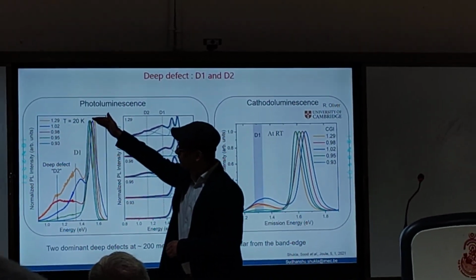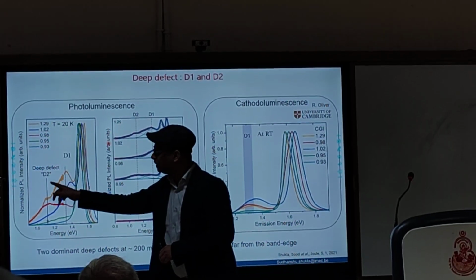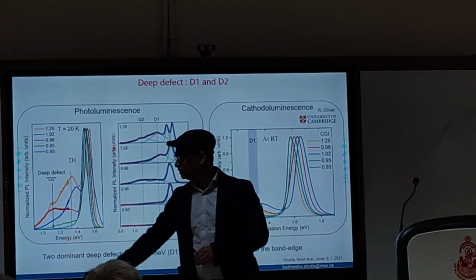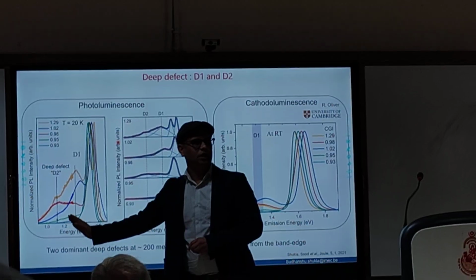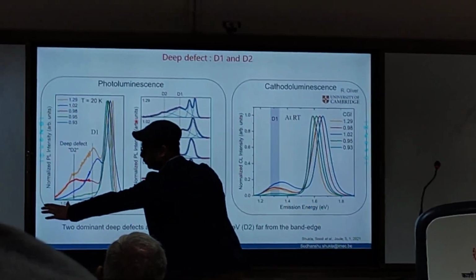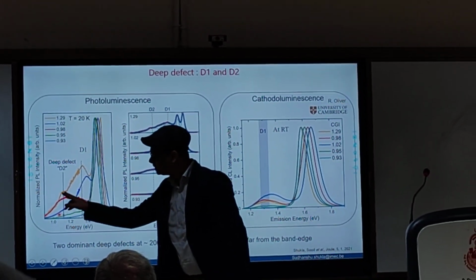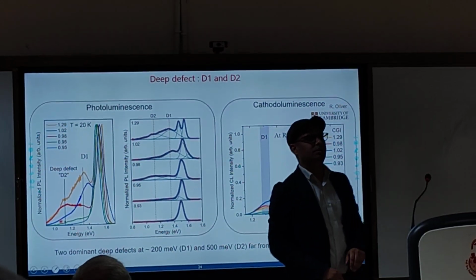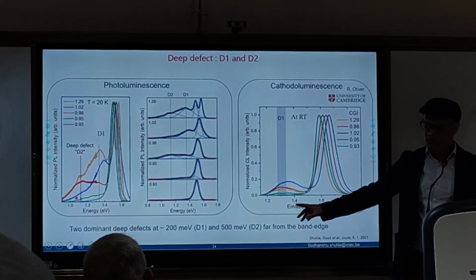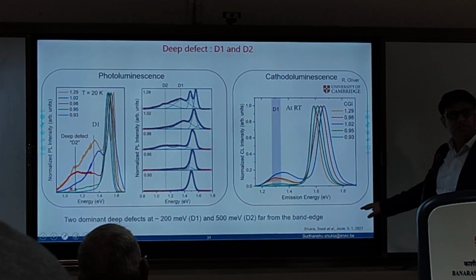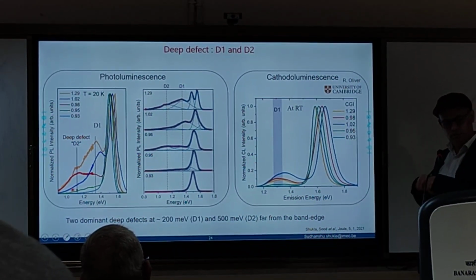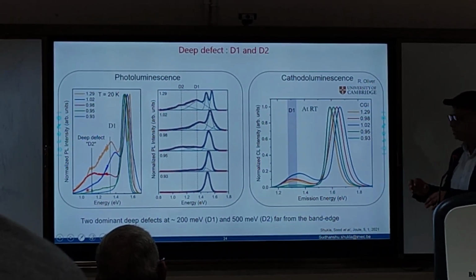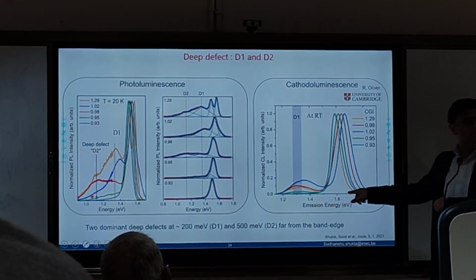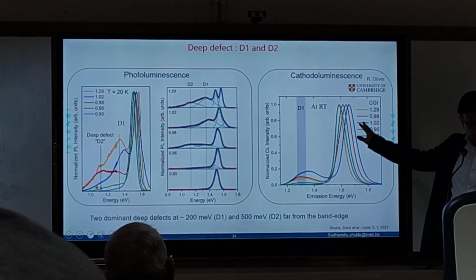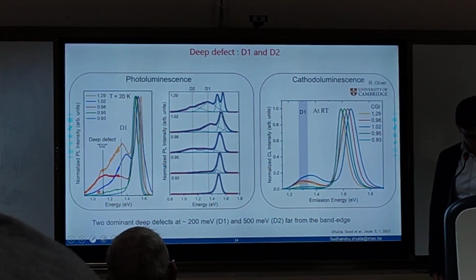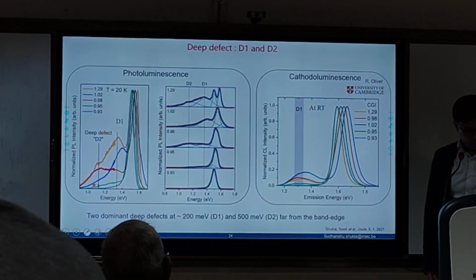Same thing, normalized. There are two defects in fact, D1 and D2. D2 is deeper, so this actually inhibits the photovoltage. So you can never get a voltage more than 1, because the carrier will just jump here and recombine. So this is one limiting factor. We checked the same thing with cathodoluminescence. This is a different technique where you bombard with electrons and see the luminescence. It also shows the same defects. A very consistent picture we get. And this is what we did with the University of Cambridge. They are fantastic at doing that.